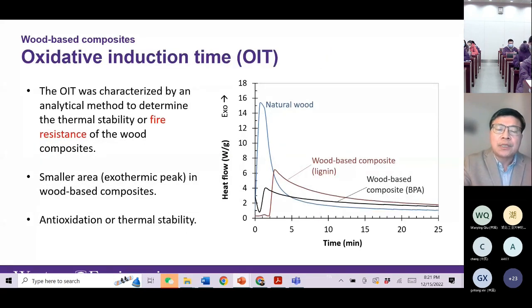And for flame resistance, or anti-oxidation, this test was done using the oxidative induction time. This shows how many minutes this material can withstand high temperature in air without catching fire, without oxidation. If you look at the peak here, the exothermic peak means some oxidation happens. So the longer the time to show the peak, the better the flame resistance property.